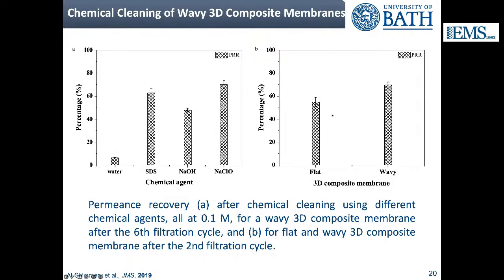And again, with the flat membrane, you recover less, because the wavy structure not only decreases the amount of fouling that is accumulated, but that localized turbulence makes it easier to dislodge the fouling that has already accumulated.